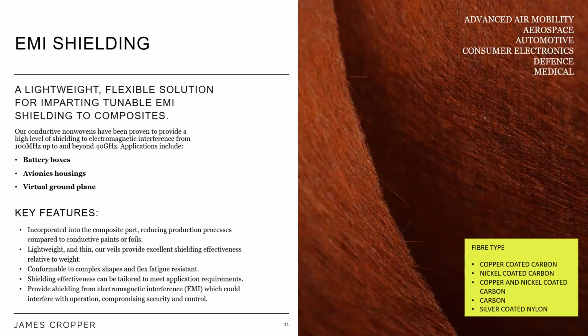The non-woven provides a network of highly conductive fibers that are surface covering while giving a uniform distribution of pores. And that porosity structure between the fiber facilitates resin infusion for simple integration in your composite part. Precise control of the non-woven weight allows the shielding performance to be tailored for your application. And the low weight solutions give weight savings while still delivering on shielding performance. Isotropic arrangement of the fibers give an even reflection profile for your composite application.